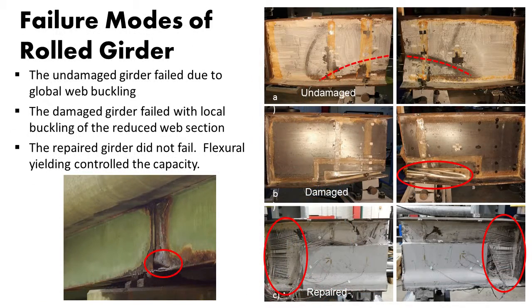So this figure shows how the three samples, the three beams, failed. The intact one failed. By the way, it's whitewashed for us to be able to see yielding on steel. We used a lime solution to be able to detect any yielding. It flakes off. You can see the global buckling of the steel web. For the beam with reduced section, all the damage was localized at the portion where we had reduced the section.